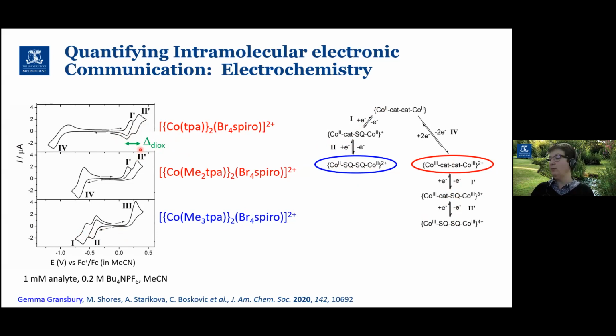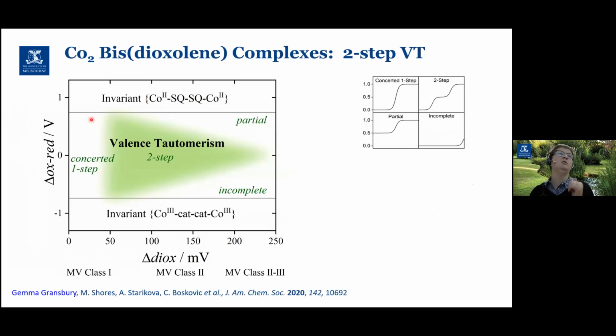So we've started calling that parameter delta diox. I've already introduced this delta ox minus red, which is the separation between the first metal-based process and the first ligand-based process. So Gemma then was able to essentially develop, using that electrochemical data, a sort of a phase diagram or a correlation diagram. We've got delta ox red, so that's the difference between the first metal and the first ligand-based redox processes, versus delta diox, and delta diox is the separation between the two dioxolene processes. So that's the measure of the degree of electronic communication.